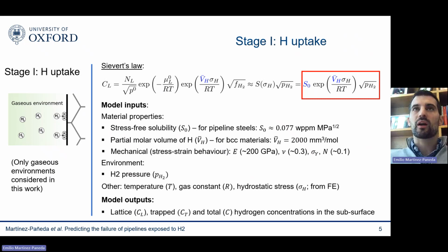I think the good news here is that we have a well-established equation for this, a closed-form solution that is Sieverts' law. And you can see it here, it basically relates the hydrogen concentration, the lattice hydrogen concentration in the subsurface of the metal, to the pressure, or fugacity if you're dealing with very high pressures. But for the pressures that we will be discussing today, pressure is fine. So this is an input. We know what the pressure of our gas is. This is the characteristic of the environment. This is what we want to obtain.